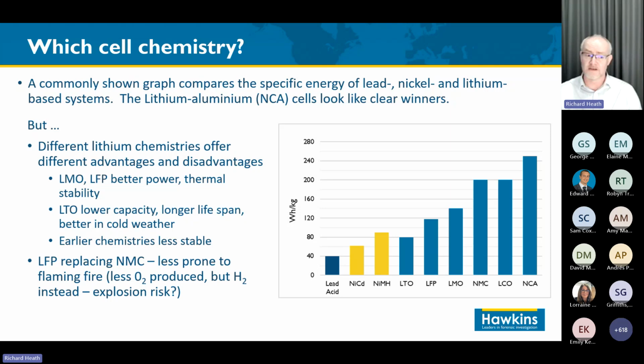But the different chemistries also have different disadvantages and advantages. So the current common chemistry is the NMC, or nickel manganese cobalt. And compared to that, the lithium manganese oxide and lithium iron phosphate cells offer better power, but also some better thermal stability. And by that, I mean they're less likely to go into thermal runaway.